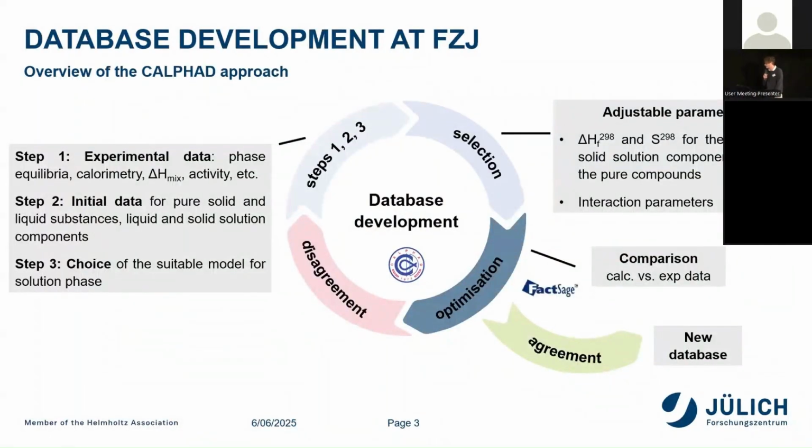On this slide here, we can see an overview of the CALPHAD approach, which is used for our database development. In the initial steps, we collate the thermodynamic data on the system, including phase equilibria, enthalpy of mixing, formation, and so on. We can also do activity.